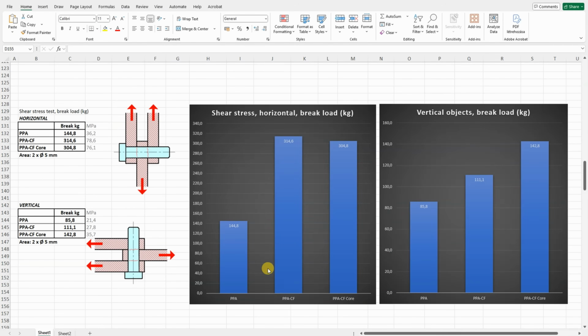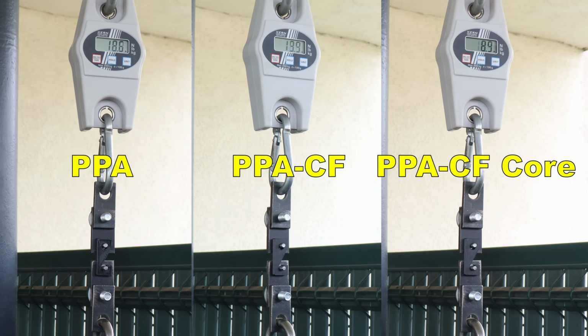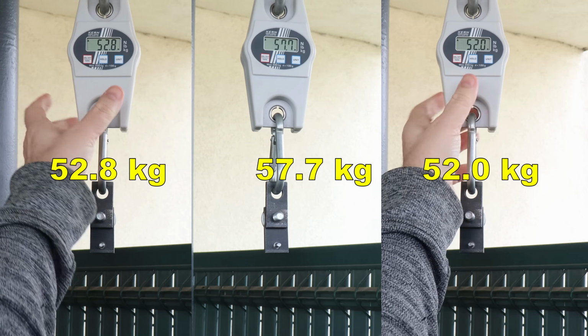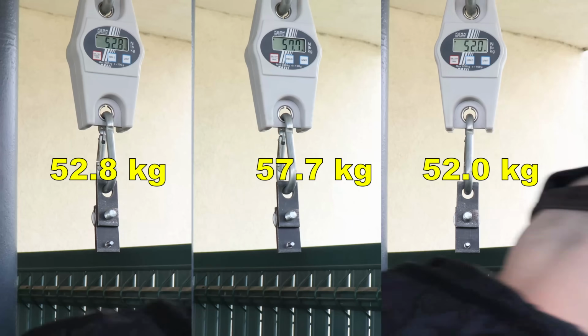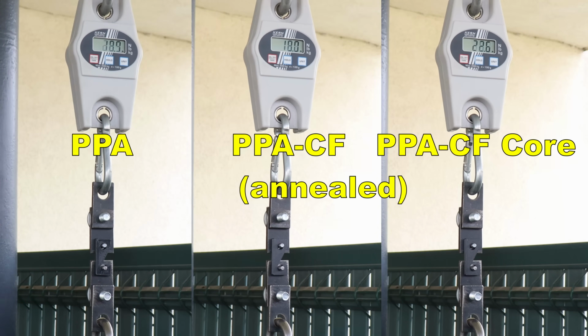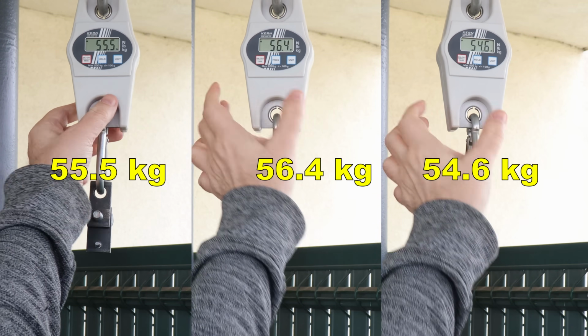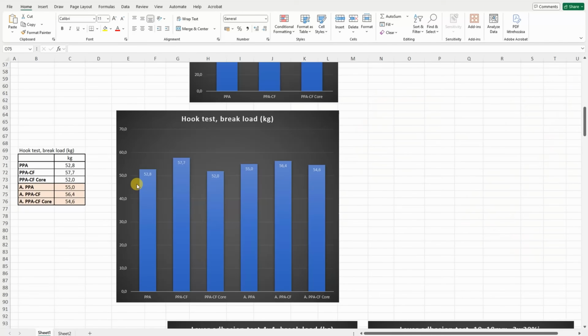With horizontally printed test objects, those carbon fibers really helps, and this we can see in the numbers. No big difference between two carbon fiber versions. With vertically printed objects, the layer adhesion is very important, and here of course the core version was the best. The hook test side by side all three materials. There is some difference, but not big. And this is the annealed version. And again we can see some difference, but nothing significant. And we can see this on the graph too.